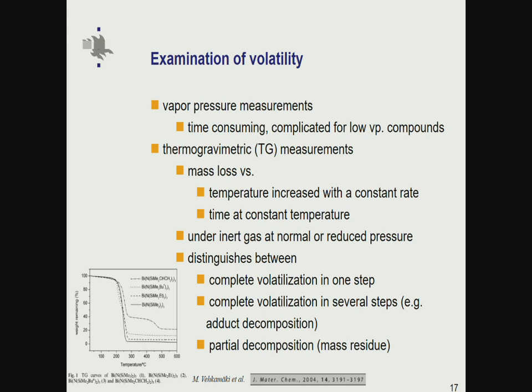volatilization in one step. For example, this solid curve here is showing what one wants to see from a good ALD precursor or MLD precursor. Once reaching a temperature where evaporation starts and going towards higher temperature, everything gets volatilized in one single step. That's an indication of a nicely volatilizing precursor. Sometimes there may be, as I show in the next slide, several steps, so there is some transition in between, but eventually everything gets volatilized, so there is zero residue being left.